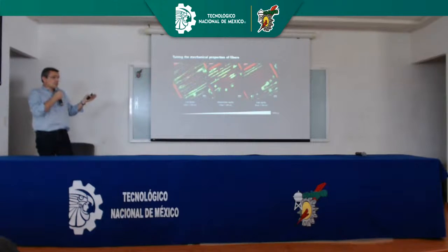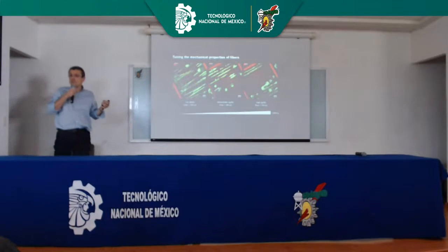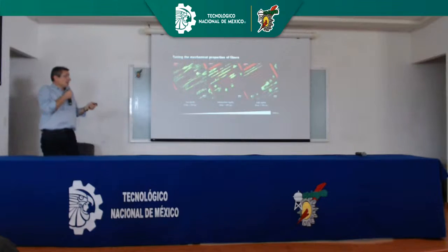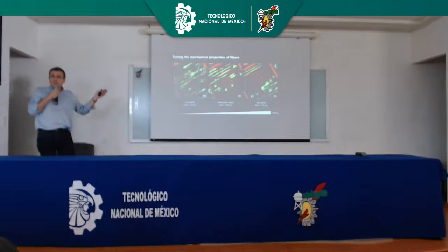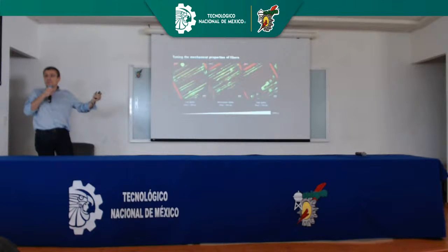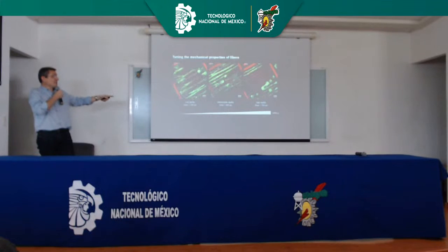We are talking about rigidity. What is nice with polymer? You can play with rigidity by controlling the number of crosslinks in your system. In other words, here we have photopolymerization. If you play with the exposure time, you can play with rigidity. At low exposure time, you will have a low rigidity. At high exposure time, you will have a high rigidity. What we can see is that when you seed cells on those systems with low rigidity, they behave completely differently from those with high rigidity.